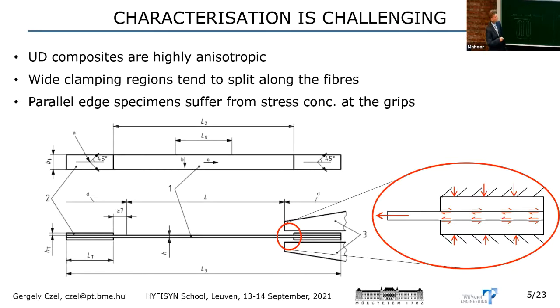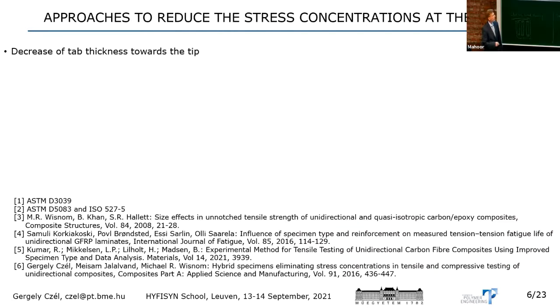Okay, this is not usually just a little bit, because sometimes, or maybe many times, it's a higher force than the actual active force, the tensile force, because of the wedge angle of the grips. So it's a quite high force, but not that harmful to our specimens. But on the other hand, these shear and normal forces or stresses are compromising the final failure of our specimens. So we normally have failure near the end tabs.